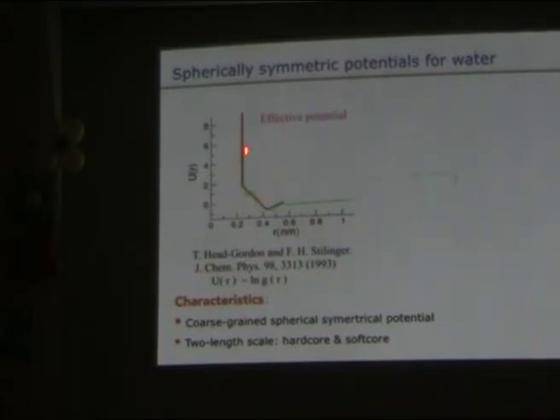two terms. One is the hardcore interaction, so basically you can mimic the strong repulsion when the two particles are moving close to each other. And then you have this kind of weak interaction between two particles. When they are at a certain distance, you can stabilize the liquid into one of this minimum. So basically the key feature is, first of all, it is coarse-grained. Second, it has spherical symmetry. And the third one is it has two length scales. So this turns out to be extremely important in our study. This is the first length scale, and this is the second length scale.